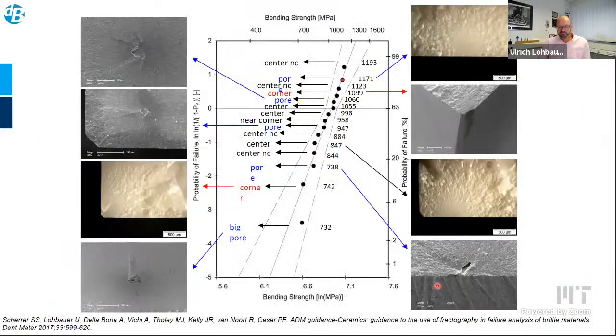I'll give you some examples that are very prominent in dentistry, but also in other fields. So this is a Weibull graph of strength distribution of a material. And this Weibull statistic provides us with a certain characteristic strength at failure probability of 63%, and also the scatter of data, the homogeneity, the Weibull modulus, on the measurement of 20-30 specimens that we use.